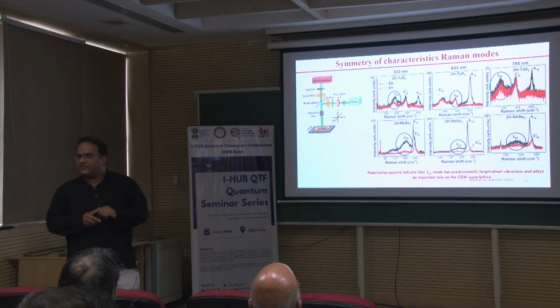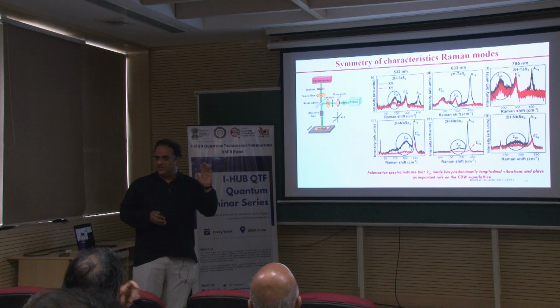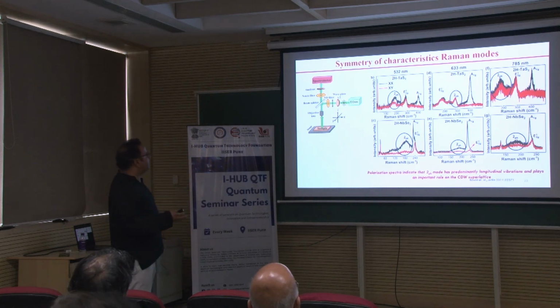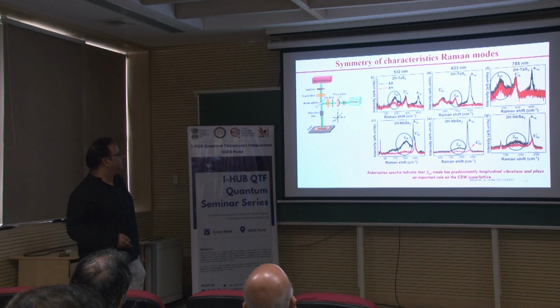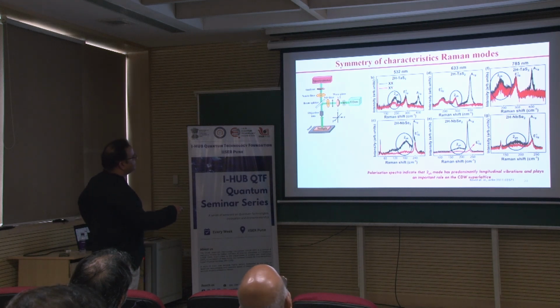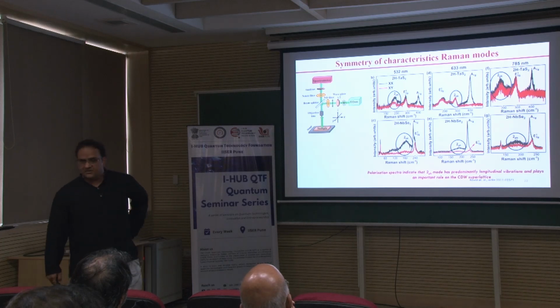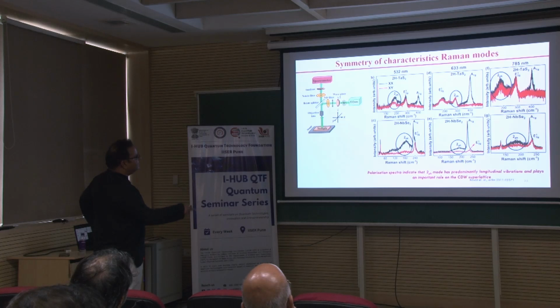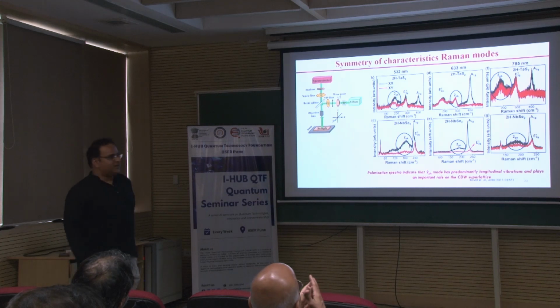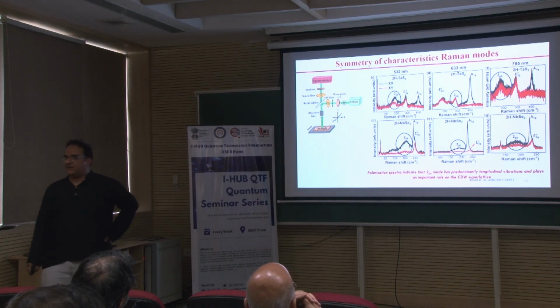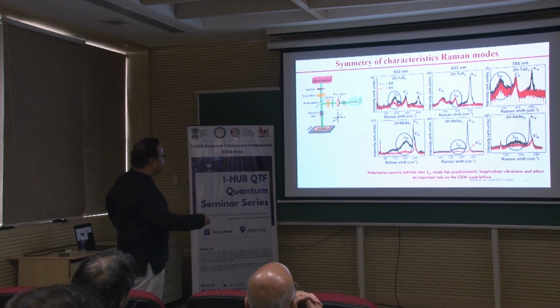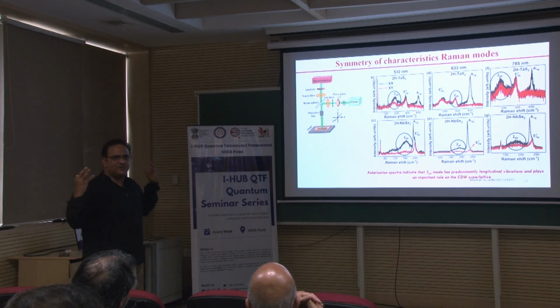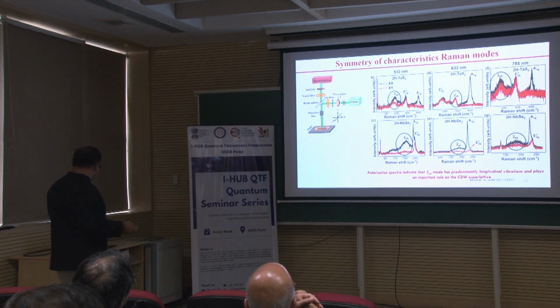Suppose you wanted to find out the symmetry of the mode, what you do is polarized Raman spectra. You do xx polarization and xy polarization. If a mode is there in both xy as well as xx polarization, you call it an Eg mode, because they are symmetric. But if it is in xx and is not there in xy, it is an Ag mode. Now, if you look at this 2 phonon mode, there is a slight change in the intensity of the mode in the xy geometry. Whether I excite with 532, 633 or 785, I see this signature in all these Raman spectra. Which means this particular mode has both symmetries, I would say, or it involves the vibration of the atoms in both directions. How does it look?